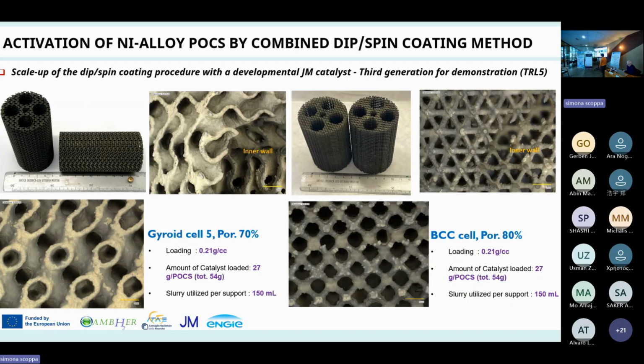We have some images that demonstrate that the coating is very good. We have a homogeneous distribution, also with the very complex gyroid structure of the catalyst inside. Also inside, here you can see the inner wall. The other one is the BCC, and the total amount of catalyst we loaded is about 54 grams of catalyst, 27 grams for each piece of POCS.